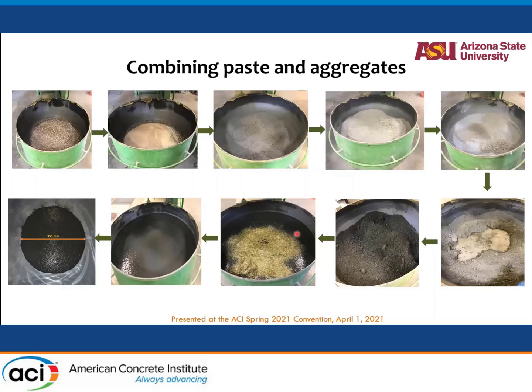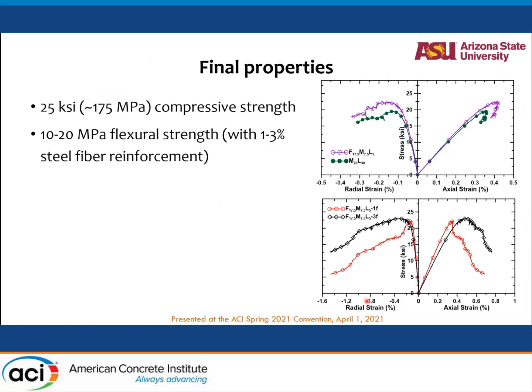I just missed a couple of pictures in between. And then you add steel fibers, you mix for some more time, you get a very cohesive, a very smooth mix, which flows quite nicely. So this is the mix design and large scale, reasonably large mixing of those mixes. Final properties, we got about 175 megapascal compressive strength for these mixes after 28 days. Some of them with higher amounts of fly ash gave close to 200 megapascal after 56 days or 90 days. Up to 20 megapascal flexural strength with 1 to 3% steel fiber reinforcement. And we see the stress strain curves for our mixes on the right here.